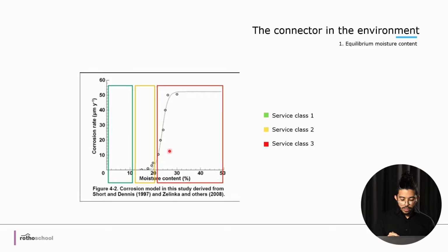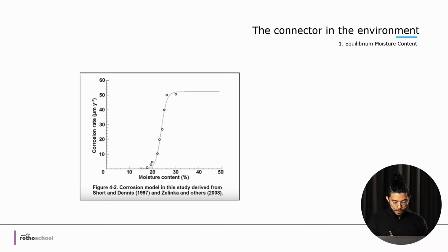And as well here, the corrosion rate goes from 10 above, so you are very sure that in service class 3 there is going to be corrosion, and very active corrosion. But in service class 2, you are in a gray area where from 10 to 16 more or less corrosion can and cannot be, and from 16 to 20 corrosion in most cases will be present. So it is a gray area where you are not sure if corrosion can or cannot happen. So this is what is present at the moment.